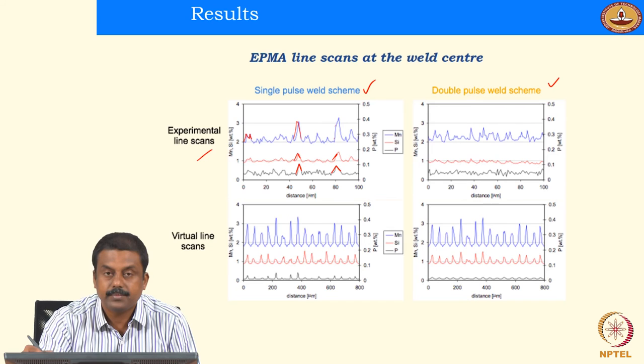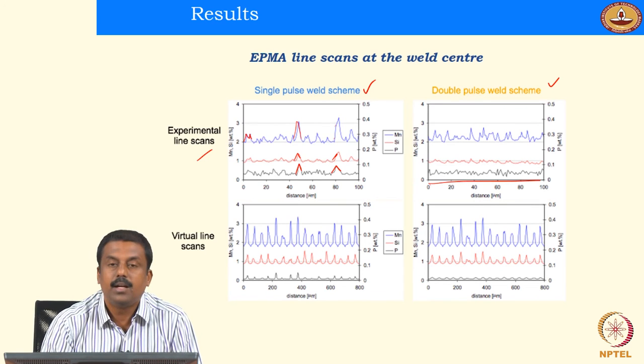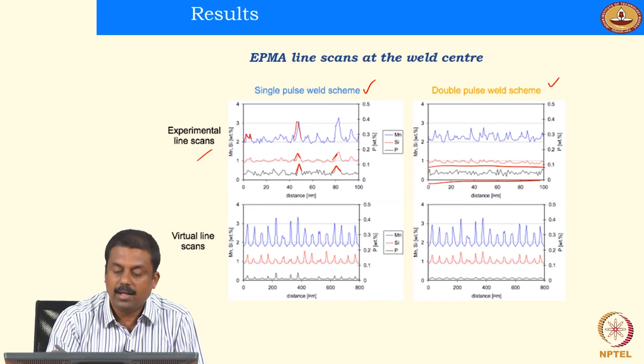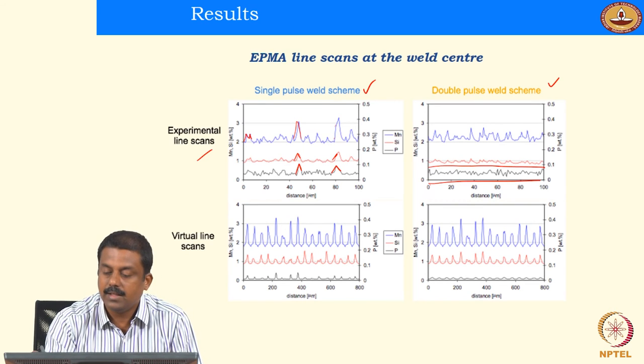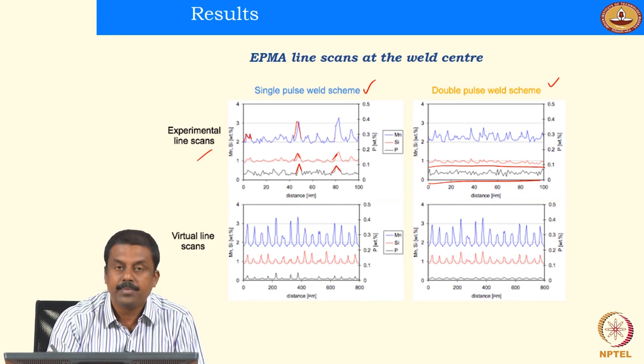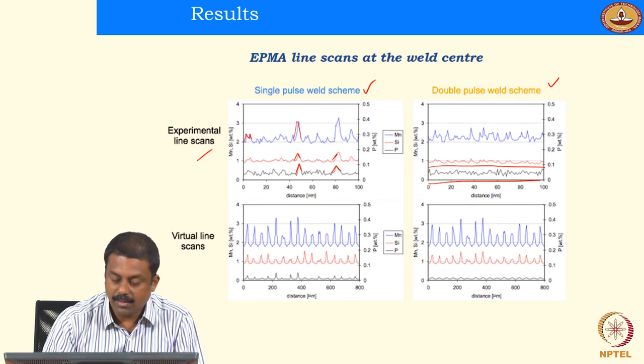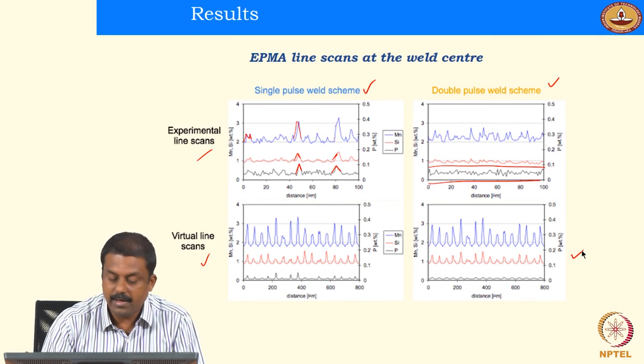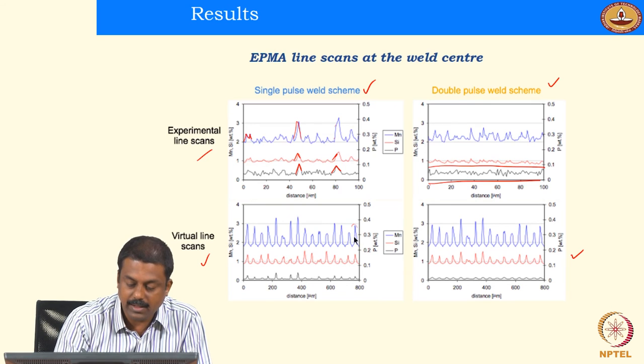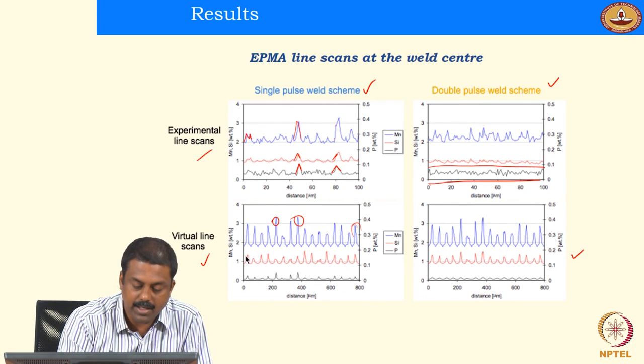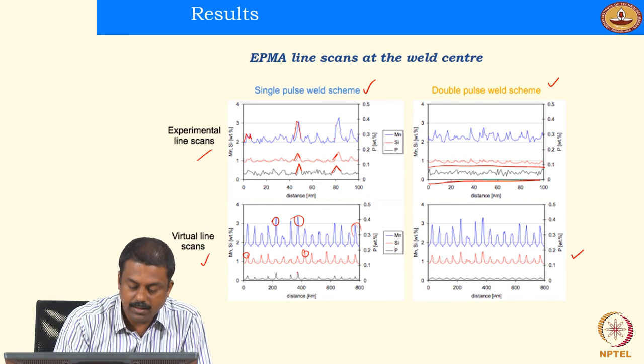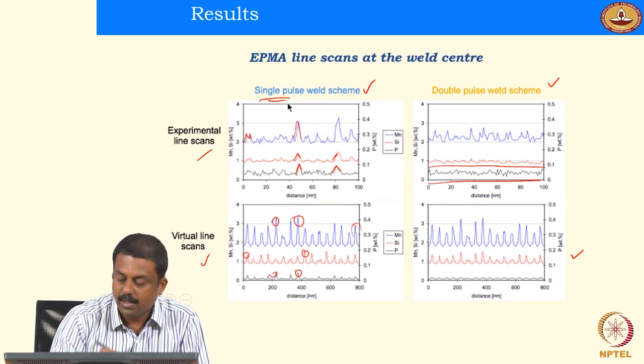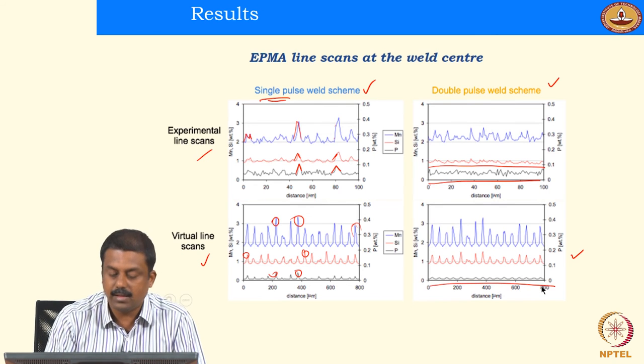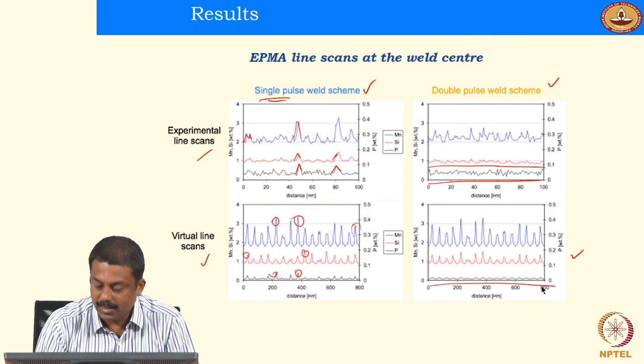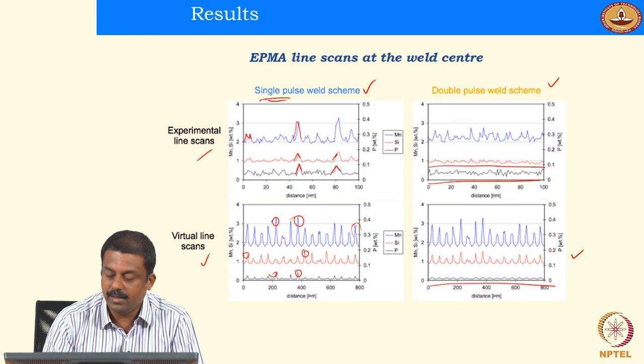Whereas after double pulsing, you see that phosphorus, silicon as well as manganese is more or less the same in almost all the regions. That means that the segregated regions at the grain boundaries are all homogenizing. That is what is also shown from the simulation results. In the simulations, what you saw here is the segregation of manganese, silicon and phosphorus during a single pulsing, whereas in double pulsing you see that the phosphorus is completely homogenizing after the second pulsing, an effect very significantly seen in the phosphorus case.